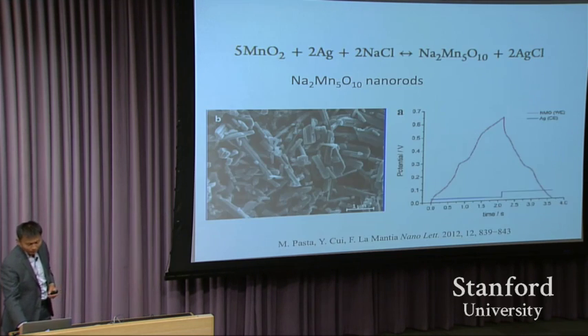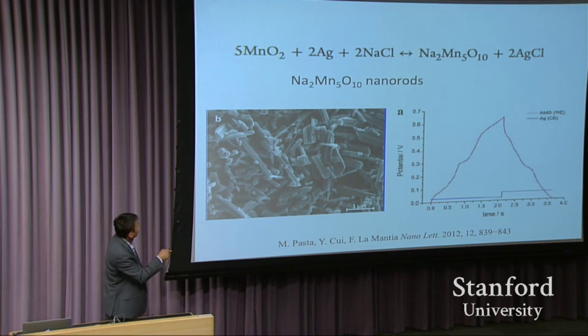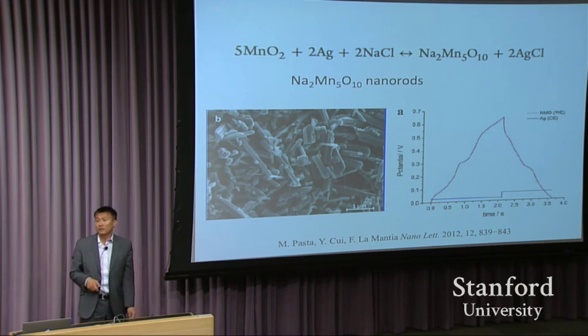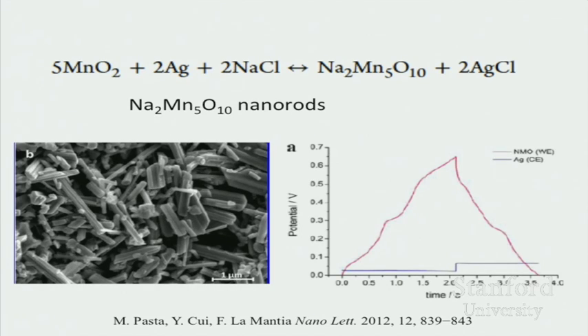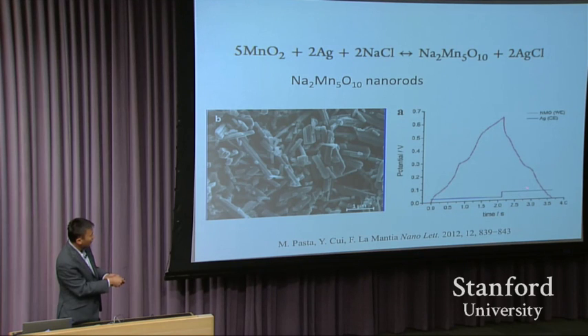So with this idea, we chemically synthesize sodium manganese oxide nanorods, shown right here. With the 1 micron scale bar, you see these nanorods, they have a diameter of a couple hundred nanometers. The reason to use nanomaterial is because of high surface area and small dimension, and the distance for sodium ions to diffuse in and come out is short, so you can minimize the kinetic loss. And you measure the voltage curve, charge and discharge. This is the curve of sodium manganese oxide. The blue is the silver chloride charge-discharge curve.